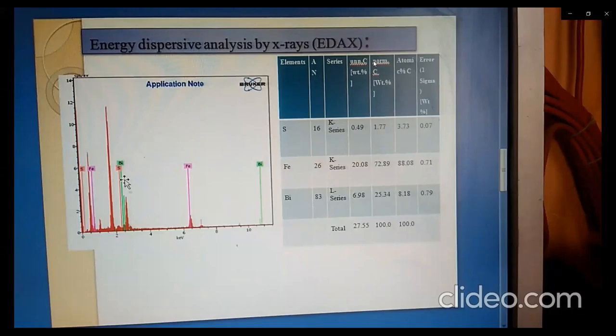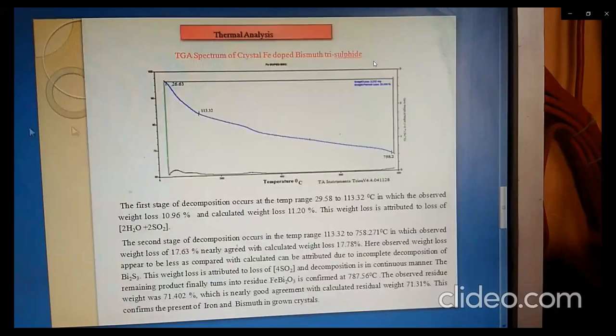Next characterization is thermal analysis, TGA. The figure shows the TGA spectrum of the grown sample. The first stage of decomposition occurs in the temperature range 29.58 to 113.32 degrees Celsius, in which the observed weight loss is 10.96% and the calculated weight loss is 11.20%. This weight loss is attributed to loss of 2H2O plus 2SO2.